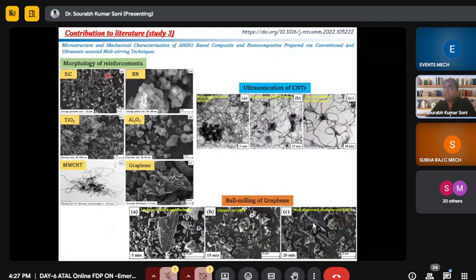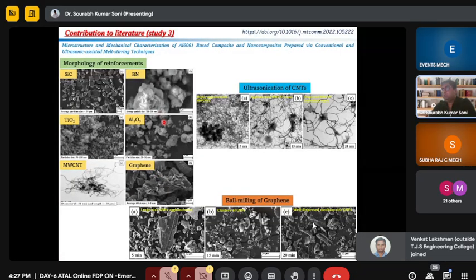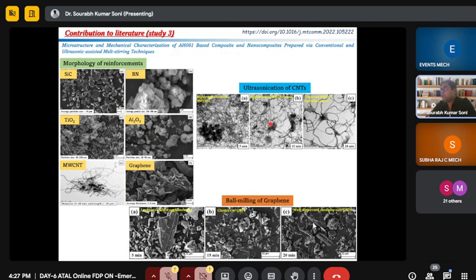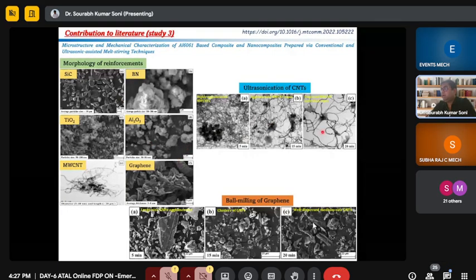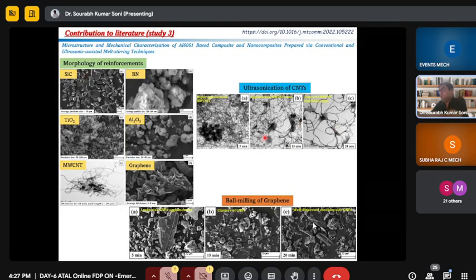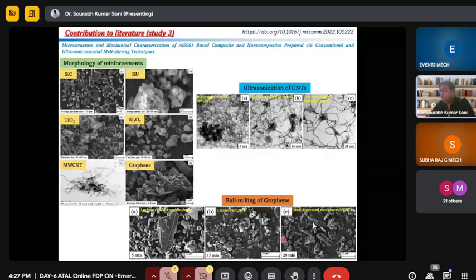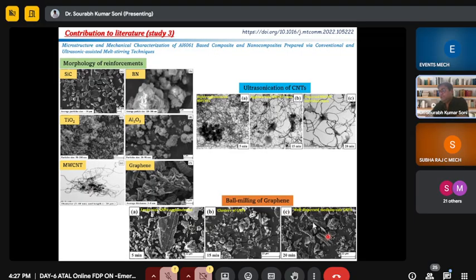I have used SiC, boron nitride, TiO2, Al2O3, MWCNT, and graphene nanoparticles to prepare the composite. And I want to highlight which composite is the best for researchers. So before fabricating, I have done the ultrasonication of CNT, and you can see that the agglomeration is decreasing as the sonication is going on. And this one is the ball milling of graphene. So as the ball milling is increasing, somewhat agglomeration is reducing, and some fine powder particles also you can observe.